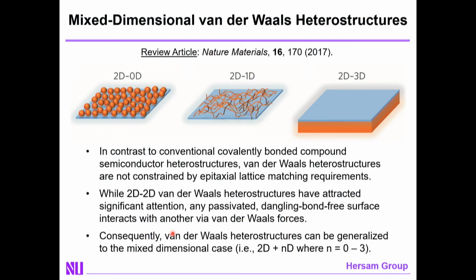And we do that as well, but what we argued a few years ago is that this concept of a van der Waals heterostructure is not limited to 2D materials, and that any passivated, dangling bond-free surface interacts with another via van der Waals forces, allowing you to generalize this concept to the mixed-dimensional case, where, for example, you could take a 2D material like molybdenum disulfide and layer on top of it a one-dimensional material like carbon nanotubes.